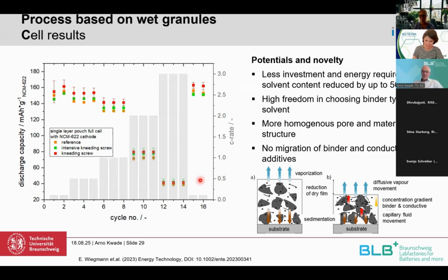Like we found for dry processing, there's no migration of binder and a very homogeneous pore and material structure. And we can use binders which are typical also for wet processing, like CMC and SBR, which are not able to be taken for full dry processing.